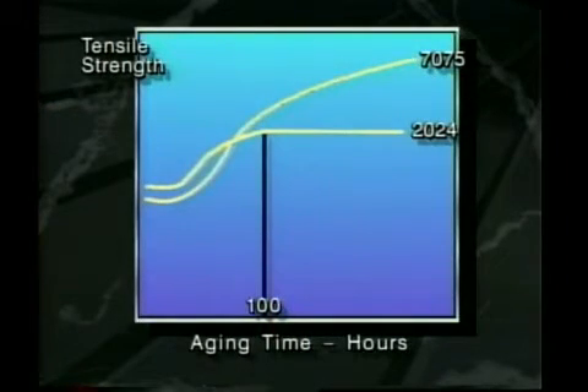In contrast to the ability of the 2024 alloy to achieve a stable, naturally aged condition, the 7075 alloy never achieves stability with room temperature aging. The natural aging reaction, which is caused by the precipitation of complex precipitates, continues to progress indefinitely, so that even after 100,000 hours, or 11.4 years, the alloy is still continuing to increase its strength level. Thus, a designer cannot effectively predict the exact performance of a T4 type 7000 series alloy in service because its properties are constantly changing with time.